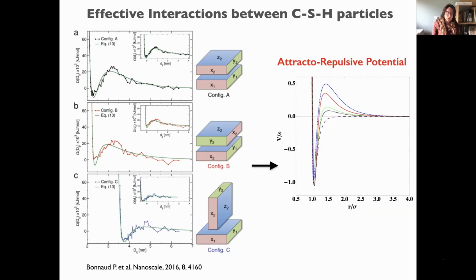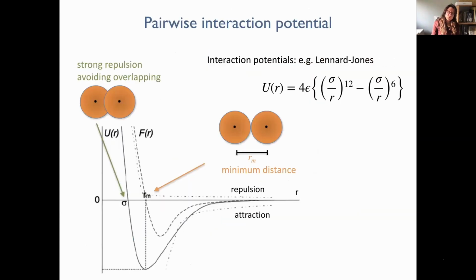Now that we know more about this, we want to move to the next scale, starting with two particles as I said earlier, and use different interactions to reach the mesoscale. The final interaction for cement is purely one with an attractive well, but before arriving there the system goes through attractive-repulsive potentials, as you see in these figures. To describe these potentials, we used a Lennard-Jones type of potential.